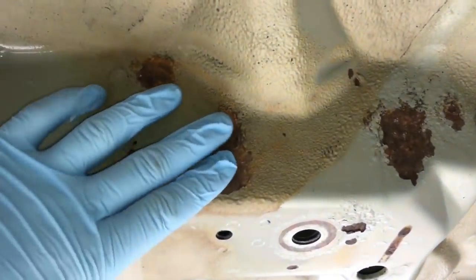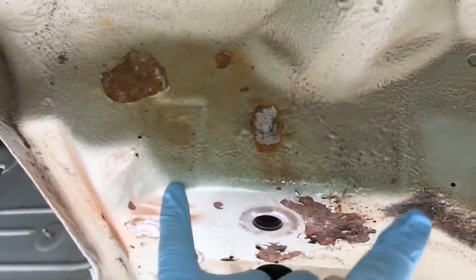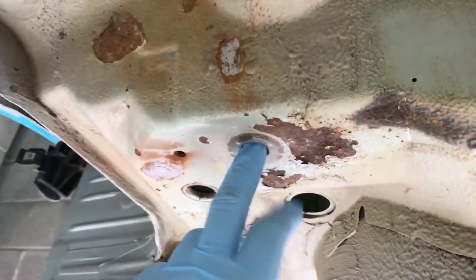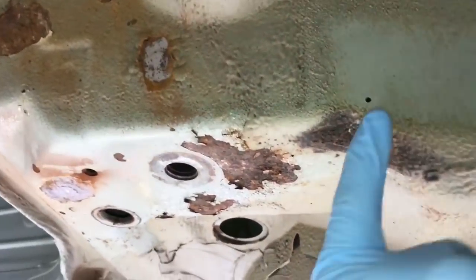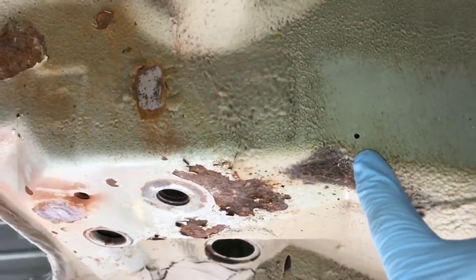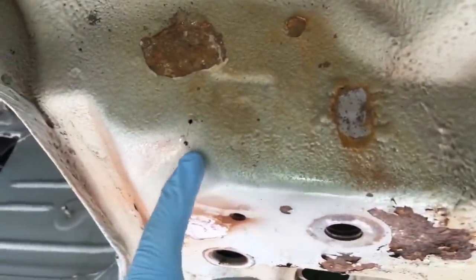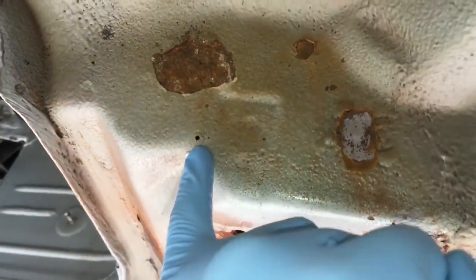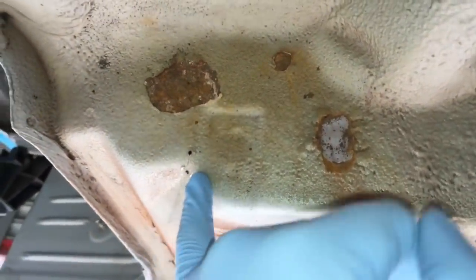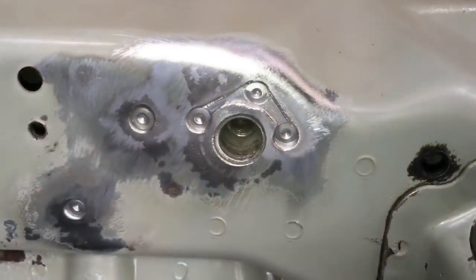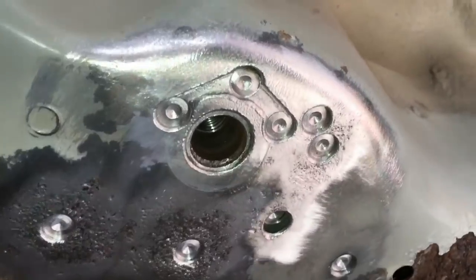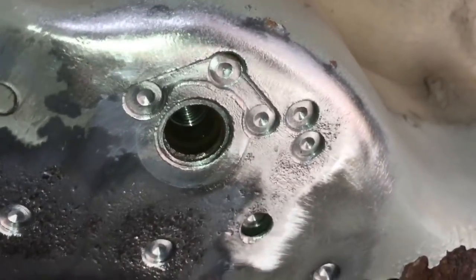Just starting to disturb the rust and corrosion, chip that off, and just found 2 more cracks on the right rear threaded mount. This one is normally not too bad, not too affected. Very small hairline crack here in the fold, which is a mirrored image of where they crack in the fold on the left hand rear mount. I've also got another one just up here again on another fold of the rear axle carrier panel. These parts are bare metalled, ready for weld through primer, and this is how important it is to keep your eyes peeled while working on these cars.